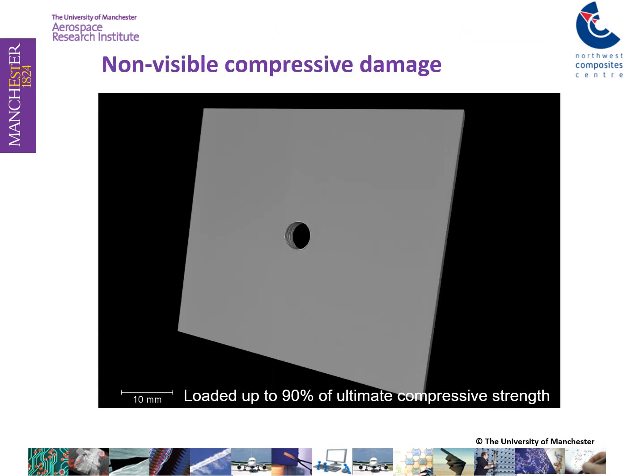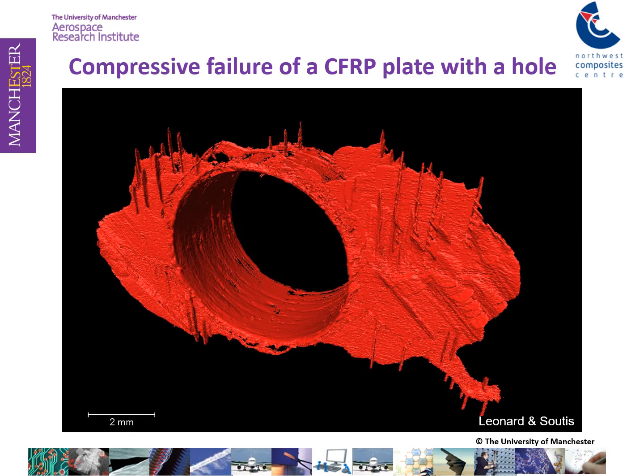Those delaminations that are triggered from those matrix cracks become more critical at the compressive loading. And here we can see a multi-directional composite laminate with an open hole loaded up to 90% of its ultimate compressive strength. There is no visible damage, but is there any damage? Of course there is. And we can see that in this slide where extensive local delamination accompanied by matrix cracks in the 0 plies and the plus minus 45 layers.